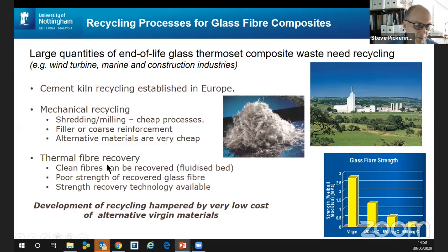You can also use thermal fiber recovery processes, and we have shown that the fluidized bed process can also recover clean glass fibers. There's quite a lot of strength reduction at high temperatures. You can see from the slide here, when you're processing at 550 degrees C, you might get the same modulus stiffness of the fibers, but there'd be a substantially reduced tensile strength. But there is technology that's been developed in the last few years to recover the strength of these fibers, and so there's a potential for having thermal recovery processes.